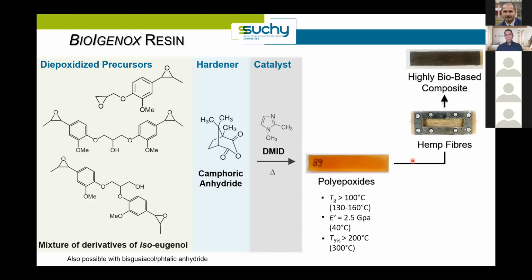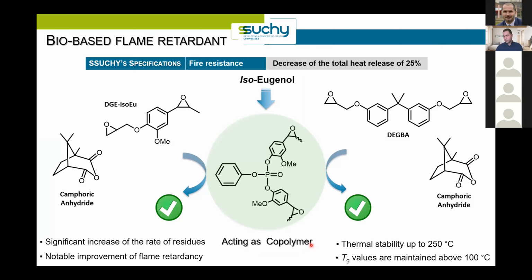Then we prepared mini samples of composite dedicated to bending test and incorporating hemp fibers. In terms of mechanical properties, the bending test showed values comparable to those obtained with DGEBA resins, demonstrating the possibility of finding alternative bio-based molecules from lignin. Also, starting from an isoeugenol derivative, we synthesized a new bio-based flame retardant during the project. And this compound can be used as a copolymer in combination with other diepoxy precursors, increasing the rate of residue and improving the flame retardancy of resin samples.